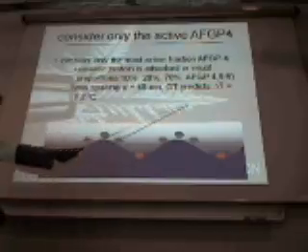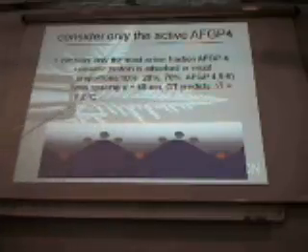If we consider only these as active, this length becomes longer. So if we consider this effect, delta T decreases to 1.2 degrees Celsius because the distance between one active protein and the next becomes longer.